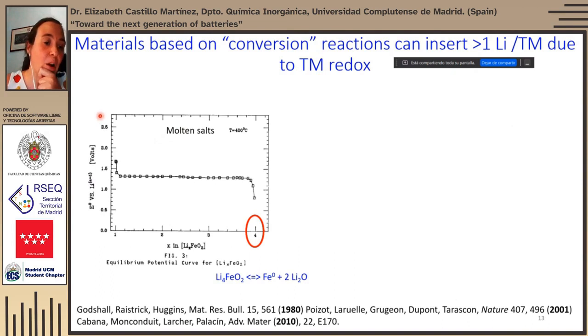Here you can see a plot in which, already in the 1980s, the insertion of up to 4 lithium atoms in lithium iron oxide, in the layered lithium iron oxide, takes place. And if we look at the chemical formula, we can see that here the iron oxidation state is 0. What happens is that we actually have iron 0 and lithium oxide.